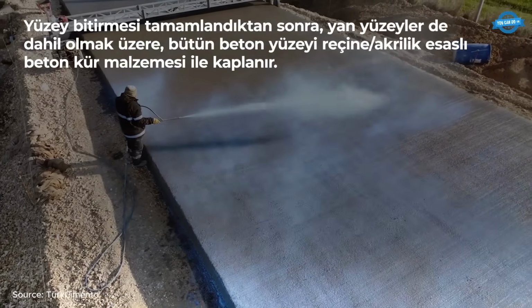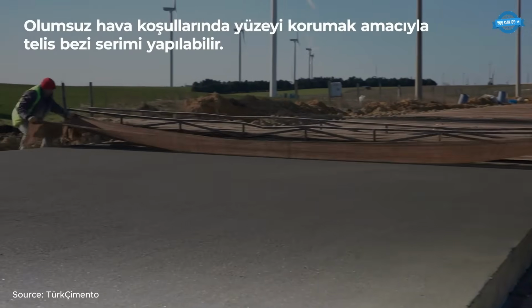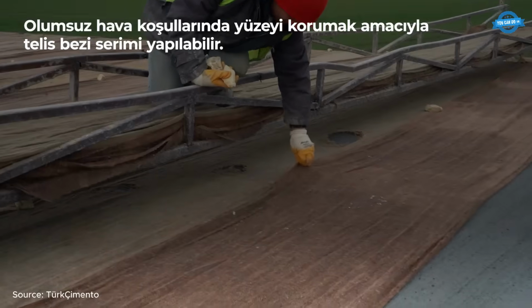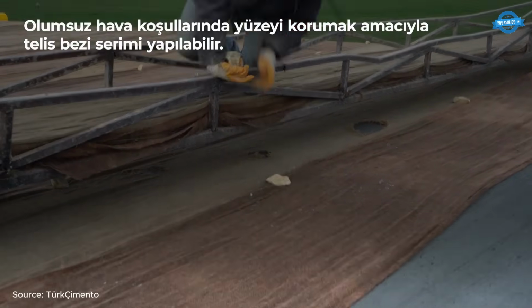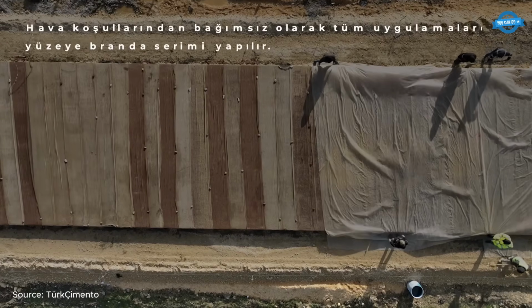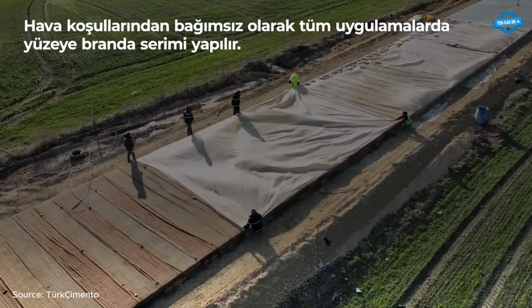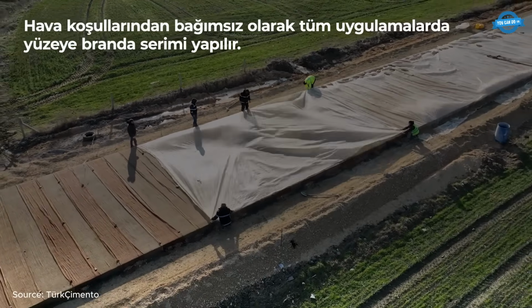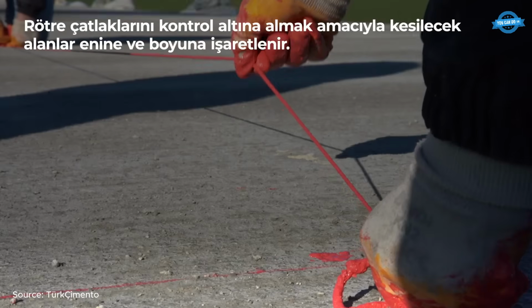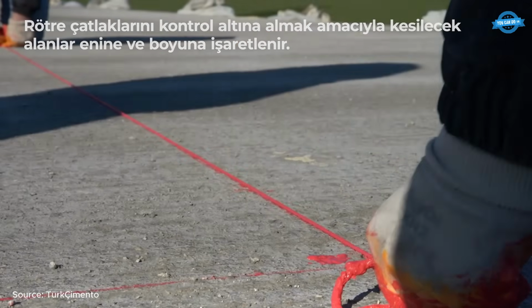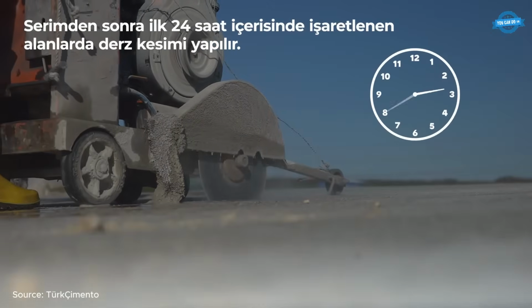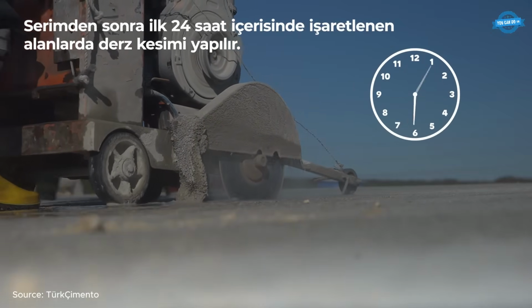After finishing, the entire concrete surface, including side edges, was coated with a resin/acrylic-based curing compound. In adverse weather, burlap and tarpaulins were used for protection. Expansion joints were marked and cut within 24 hours of placement to control shrinkage cracks. This process ensured a durable, long-lasting, and cost-effective concrete road.